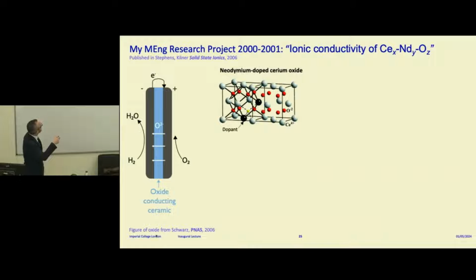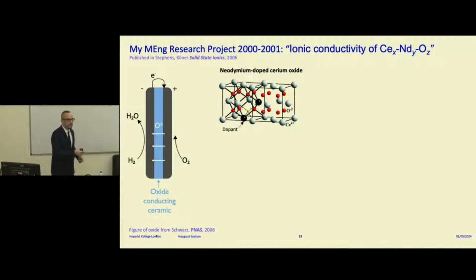Usually when you put in a dopant, you make a vacancy, like a hole in the structure. When you heat it up, you'll find the oxygen ions go through this. This is really important in order to allow this fuel cell to work. Usually they work at several hundred degrees Celsius. There are a lot of people interested in getting the temperature to go lower for many practical reasons. So what you want is to get the oxygen to move as easily as possible.